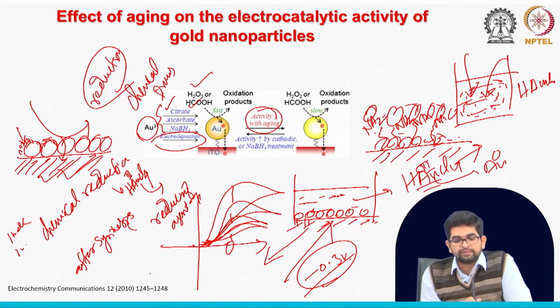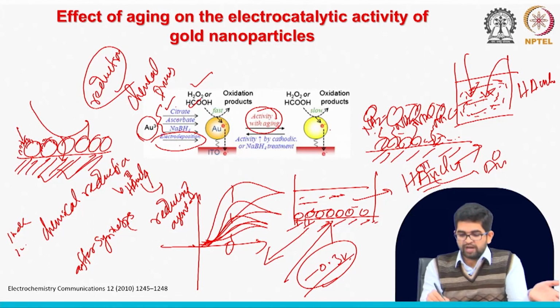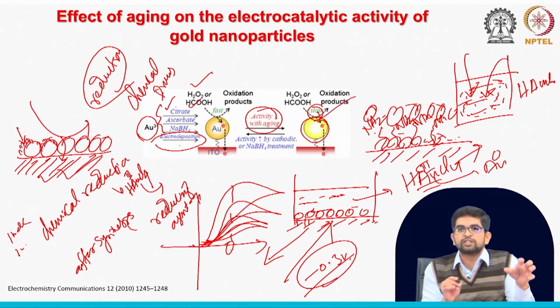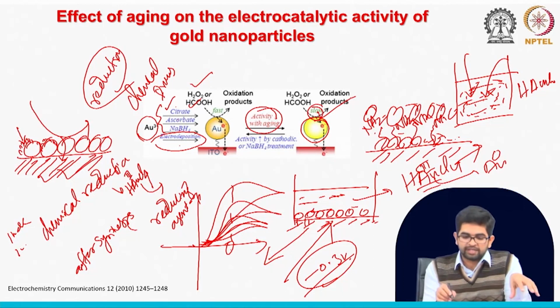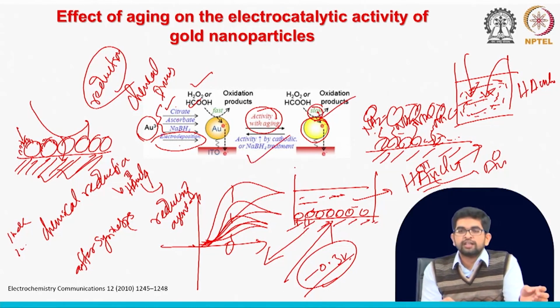This is one of the causes, the contamination. And another reason, as I told, is that if you have a nanomaterial coated electrode surface and you are getting a very slow electron transfer rate, meaning the electrocatalytic activity of your sensor surface is very low, and you want to tune its activity to a high electrocatalytic activity, then you can add just sodium borohydride.